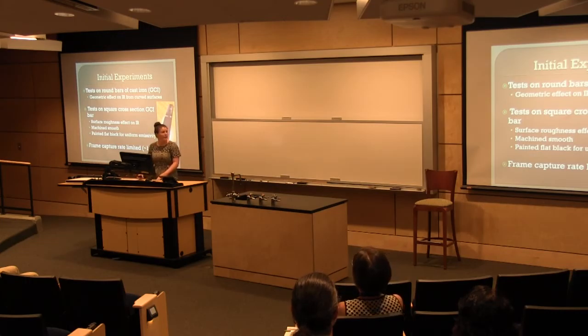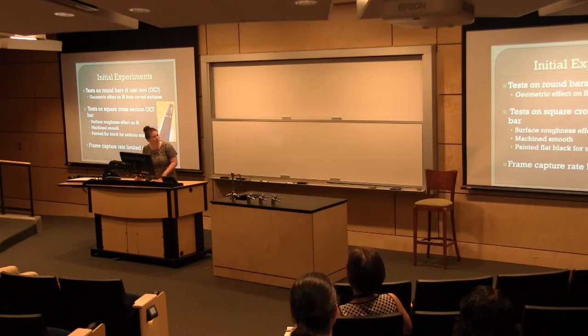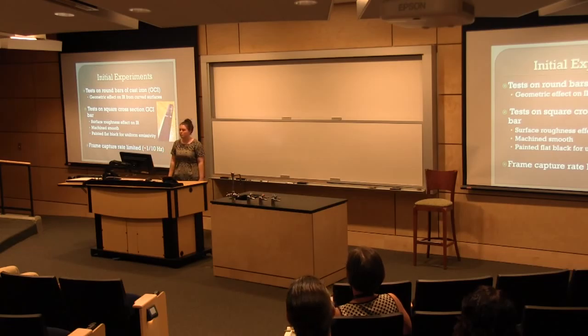So this image here is actually 4 bars lying next to each other with the flat black, and you can see the original metal on the top there. This is what our test subjects actually look like. And then you'll see there's a band of the metal going across right next to the flat black, which is what we're using to take our measurements off of to measure different spot temperatures throughout the bar.